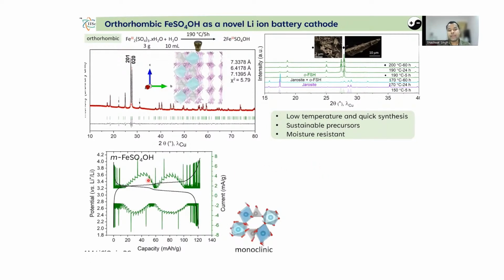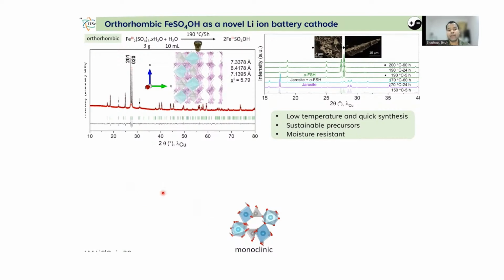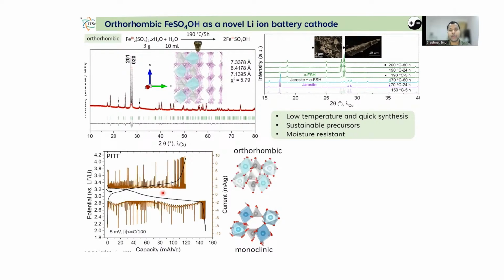Now, once again, the lithium insertion goes through a very sharp two-step biphasic reaction as shown here, as also proved from the PITT curve, where the current relaxation is non-Cottrellian in nature. Compare that with the orthorhombic FeSO4OH, where the first step is showing a little sign of biphasic reaction. However, the solid solution region is more. From the next step onward, or in the subsequent cycles, it follows a solid solution reaction mechanism.